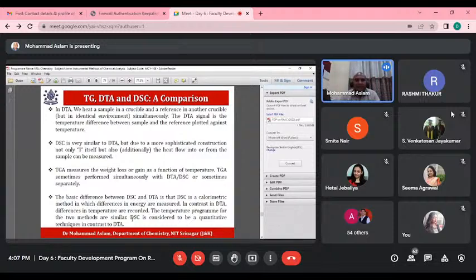TG we have studied can only measure the weight loss with respect to temperature. DTA and DSC provide useful information about the materials. Phase transitions or any heat capacity or change in phase of materials can be studied. But the basic difference between DSC and DTA is that DSC is a calorimetric method, so it provides the heat flow, or directly we can calculate the energy associated with the phase transitions. But in case of DTA, we cannot, because DTA is a simple thermal technique. DSC is a calorimetric technique, so heat flow cannot be calculated by DTA.